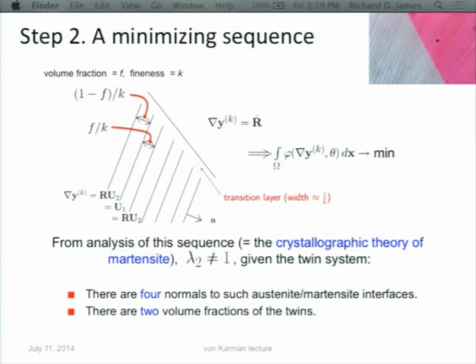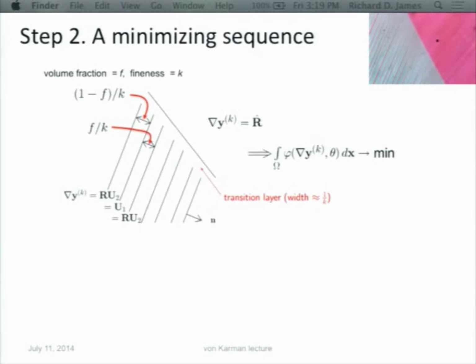So, but there's one thing about that calculation that does not agree with experiment. It says that you have to make these bands infinitely fine to drive the energy to 0. And of course, you can see from the picture, they have a certain fineness. And that's also understood in the sense that it's believed that there's a small, maybe the bigger picture would be better.